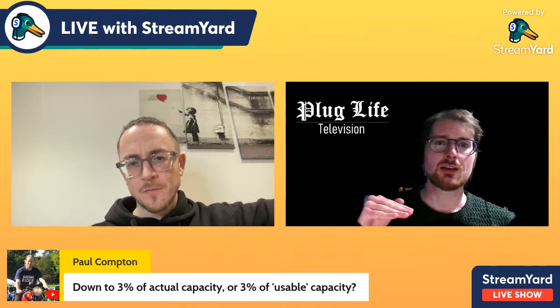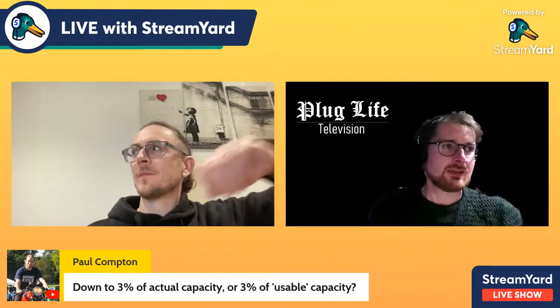Anyway, the point is that you compare that to the poster child of over-engineering, which is the Chevrolet Volt or Vauxhall Ampera, not to be confused with the Ampera E. So yeah, Chevy Volt, Vauxhall Ampera, that had a state of charge buffer at 80% of its true capacity for the top end and 20% of its capacity for the bottom end. So it only used the middle 60% of its true capacity. And that's why there was one over in the States, owned by a GM employee, which had done 400,000 miles, and the battery was still allegedly reporting 100% state of health, or at least 100% usable capacity. It may be that the BMS had gone, okay, we can start eating into these buffers as the capacity shrinks, because it's on the way out, but we can at least preserve that experience of having that amount of range.